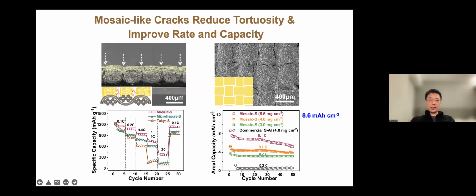And then what we get is that even with a very thick electrode, we still get a very nice and decent capacity. You see that at over 6 milligram, you get about 1,000 milliampere hour per gram, right? So this is pretty high considering the electrode is extremely thick. Of course, not all cracks will work. If we crack it as normal without control, you don't really see any good results, and the reason is the abnormal and irregular expansion that creates extra cracks.